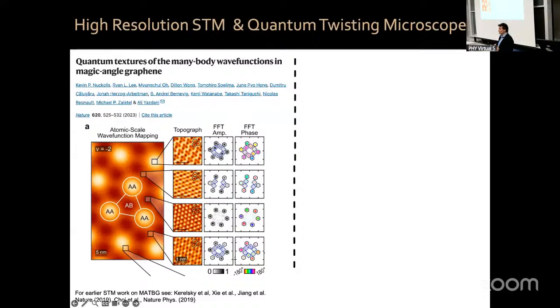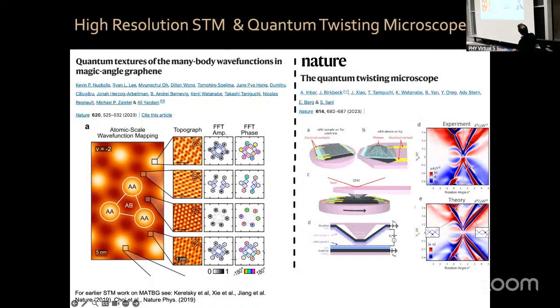Then the group of Shahal Ilani invented the quantum twisting microscope. In this twisted bilayer structure, rather than having the two sheets fixed together, you have one graphene sheet on a substrate, and the other graphene sheet placed on an atomic force microscope tip that you can bring to the other graphene sheet and rotate in situ. So we're able to control the relative twist angle between these two crystalline structures in situ. In my devices, the angle is fixed once I make the device. With this technique, you can rotate it in situ and look at the electronic properties of the material as you rotate it.